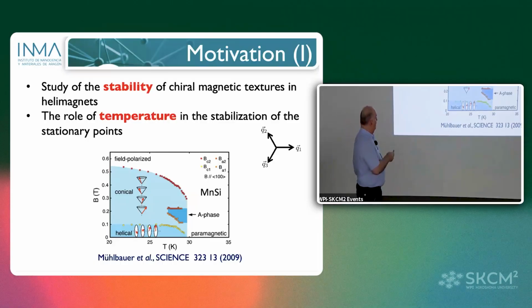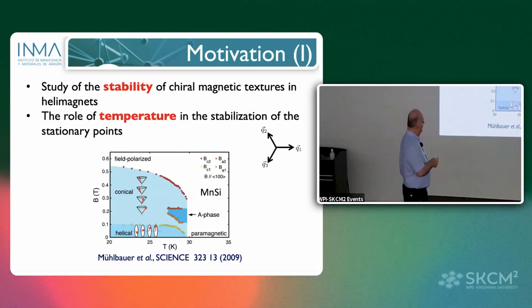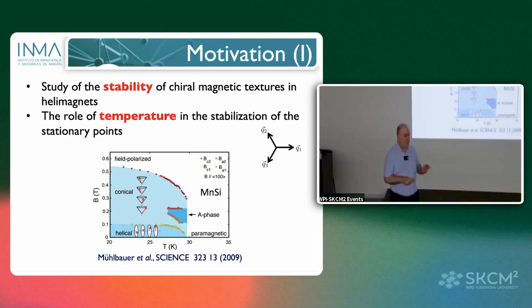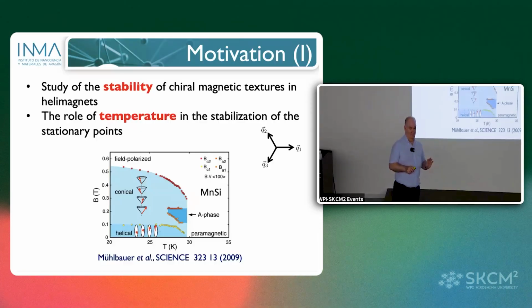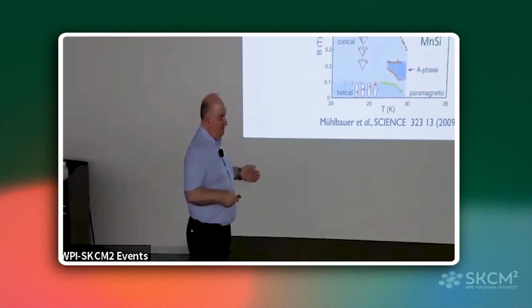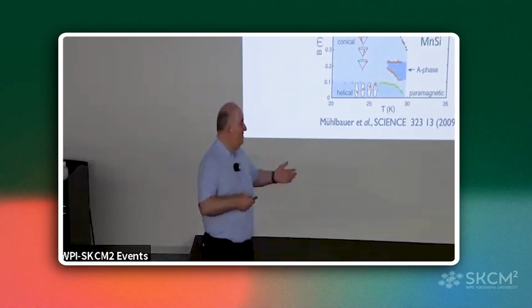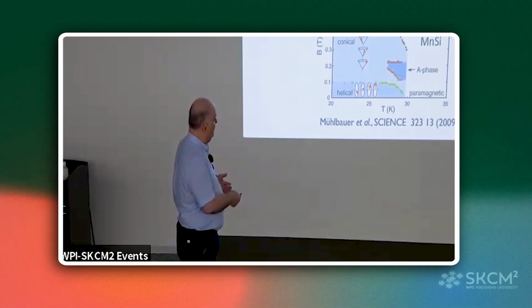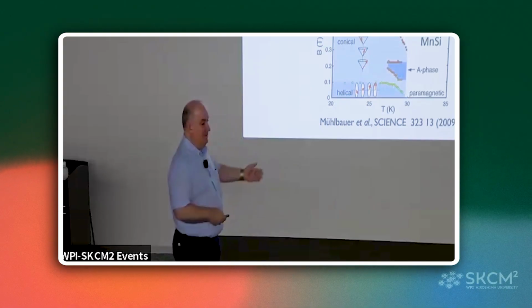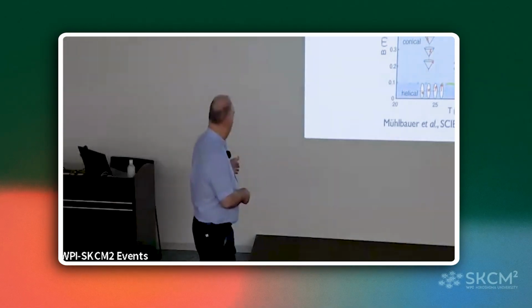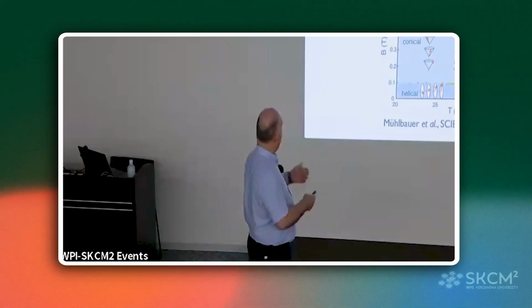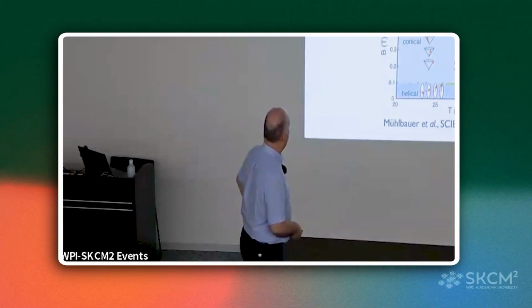Till that moment, the cubic helimagnets and the uniaxial helimagnets were not studied, including the temperature in the calculations. Theoreticians solve the Hamiltonians, but at zero temperature. And here we wanted to see what happened when you include the temperature, because all the experiments are done at finite temperature, 30 Kelvin, 29 Kelvin. This is not zero temperature. And then you will see later that at zero temperature it's impossible to find skyrmions. Then this was our main goal at the beginning.